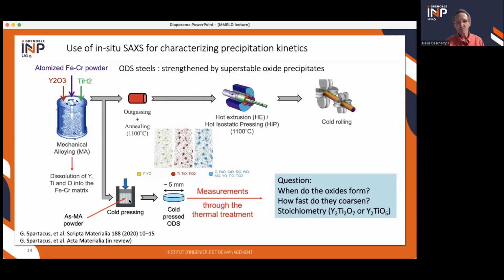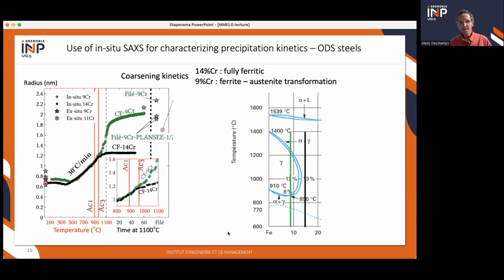So what we did was to cold press the powders from mechanical alloying, which gives you cold pressed materials that you can handle. And then you can go through it with small angle X-ray scattering and measure through the thermal treatment the kinetics of precipitation within these powders. And then you get really interesting findings.